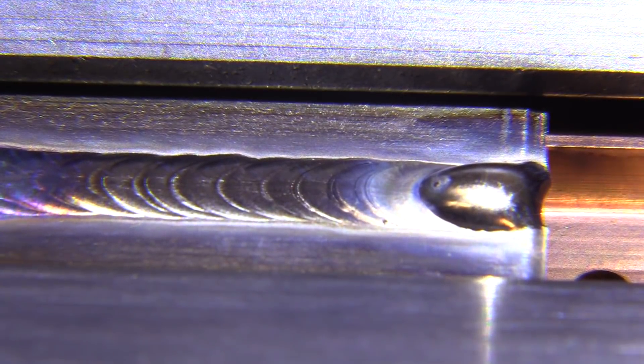Well, I captured this additional arc shot here of welding to a tack and I was a little hotter and let it run up in there a little bit farther than on the previous one. But it's just a good example of how it gives you that extra, I don't know, half a second or maybe even less to let off the pedal and having that little bit of a heavy tack there sometimes makes all the difference. Even though the code allows you to pretty much melt that in the way on a test piece, that's not something you want to do on an actual aircraft part. So, it's just a good technique for the test as well as actual parts.